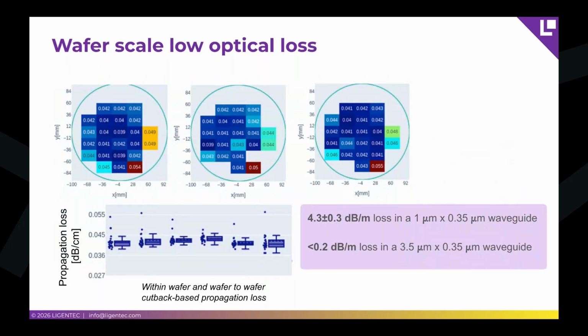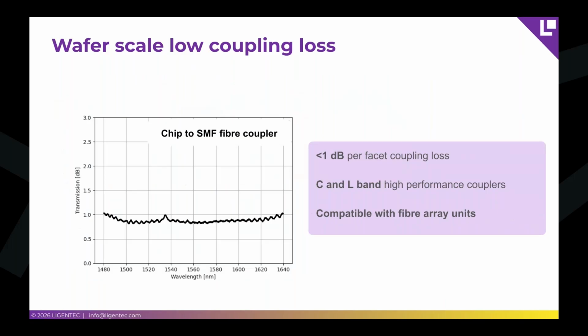So we have here on the top, we see three different 200 millimeter wafers with the statistics of the optical losses based on cutback structures that give us around 4 dB per meter in 1 micron by 350 nanometer wide waveguides, and we can also go down to 0.2 dB per meter loss in a wider waveguide. The coupling of the fiber to a chip is below 1 dB, and we are working on solutions to get even lower than that in C and L band, but also in other bands like O band down to the visible, where we have reached coupling losses way below 1 dB per facet for SMF fiber.